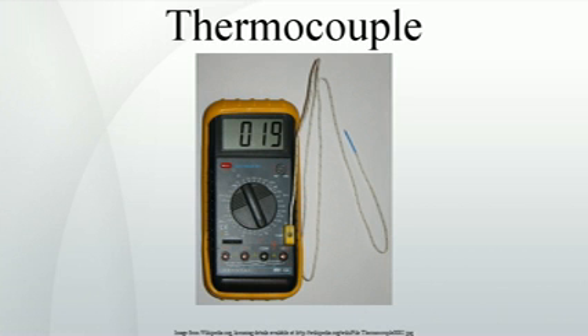Aging of thermocouples. Thermocouples are often used at high temperatures and in reactive furnace atmospheres. In this case the practical lifetime is limited by thermocouple aging. The thermoelectric coefficients of the wires in a thermocouple that is used to measure very high temperatures may change with time, and the measurement voltage accordingly drops. The simple relationship between the temperature difference of the junctions and the measurement voltage is only correct if each wire is homogeneous, uniform in composition.